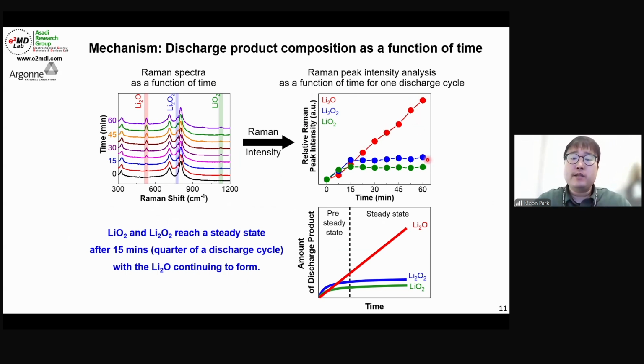So from the in situ DEMS and titration, we got to know that this is a 4-electron reaction, and it looks like lithium oxide is the major discharge product. And that's the result. This shows, every 7.5 minutes, how much the discharge product has grown over time, so it shows us the process of discharge product formation.